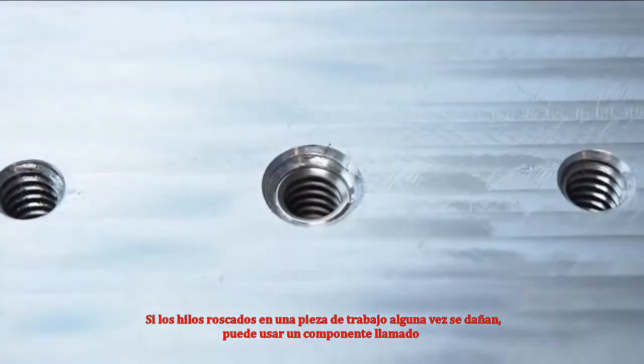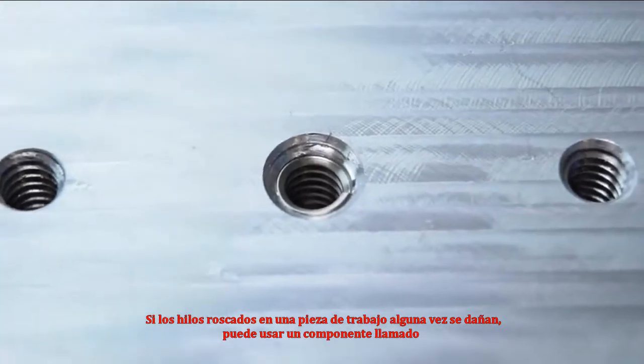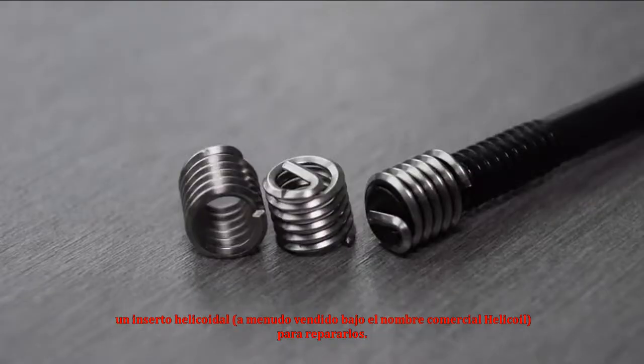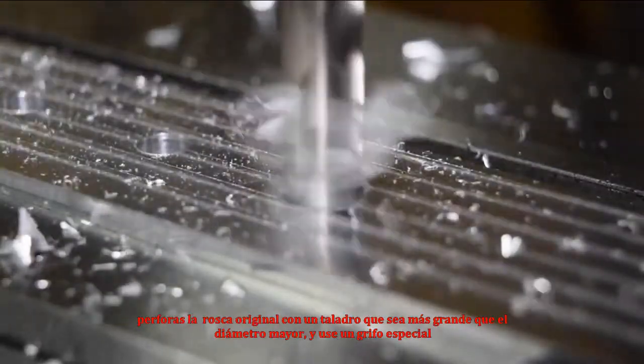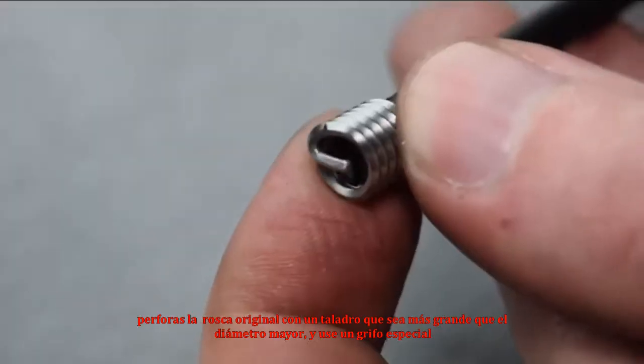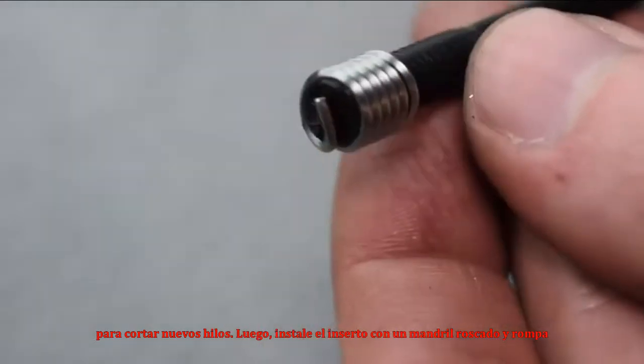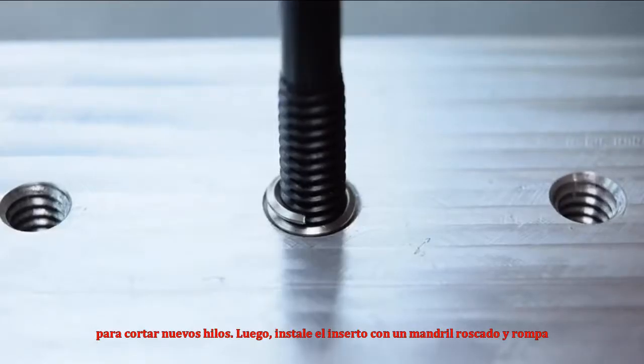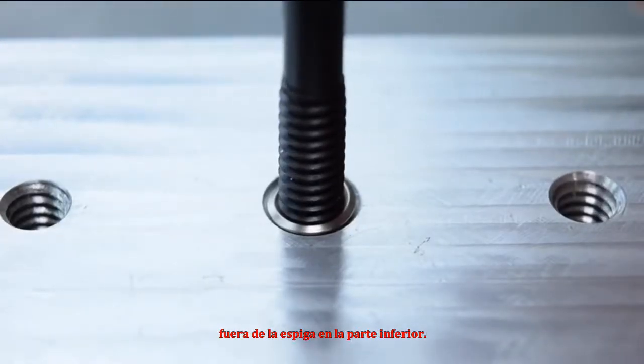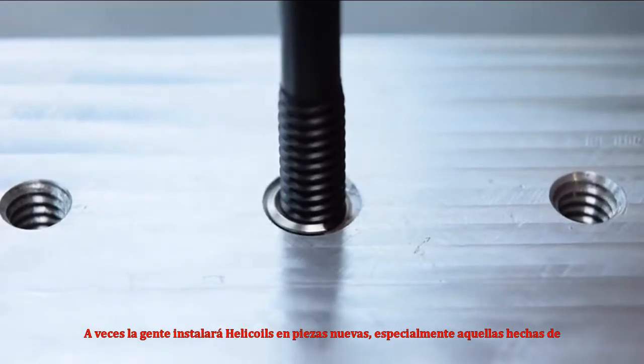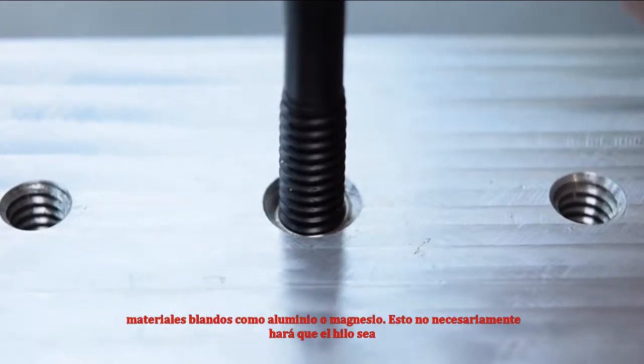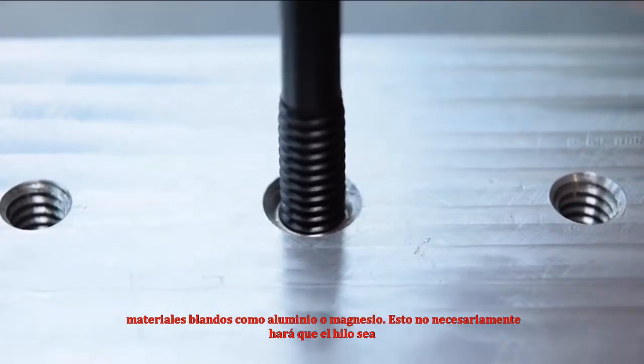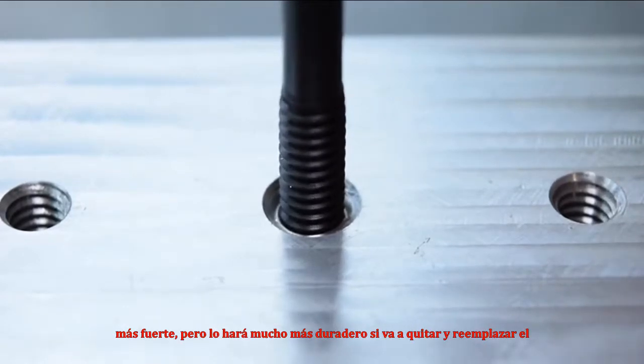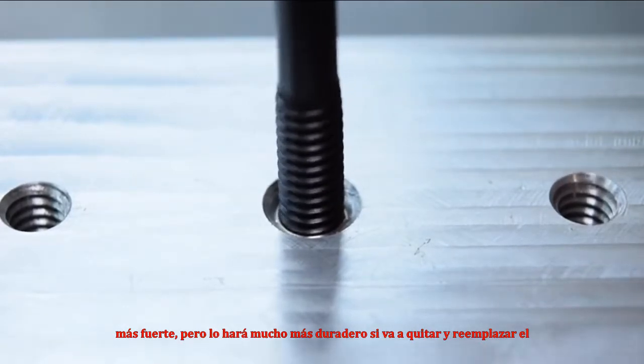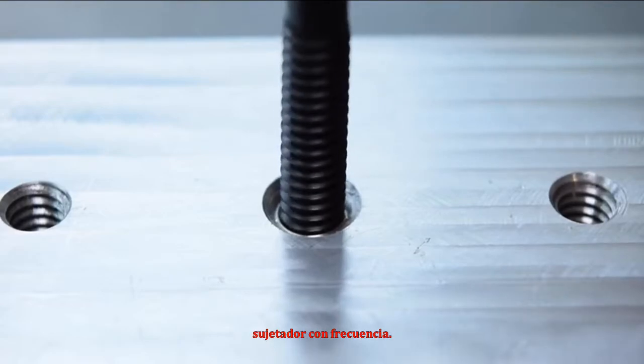If the tapped threads in a workpiece ever become damaged, you can use a component called a helical insert, often sold under the trade name helicoil, to repair them. You drill out the original thread with a drill that's slightly larger than the major diameter, and use a special tap to cut new threads. Then, you install the insert with a threaded mandrel and break off the tang at the bottom. Sometimes, people will install helicoils in brand new parts, especially those made of soft materials like aluminum or magnesium. This won't necessarily make the thread any stronger, but it will make it a lot more durable if you will be removing and replacing the fastener frequently.